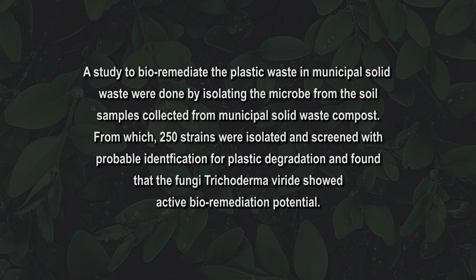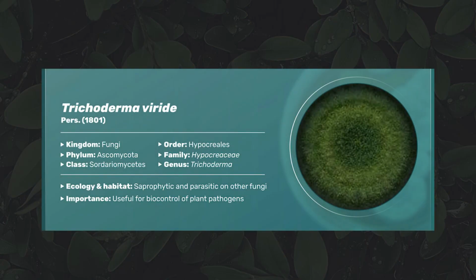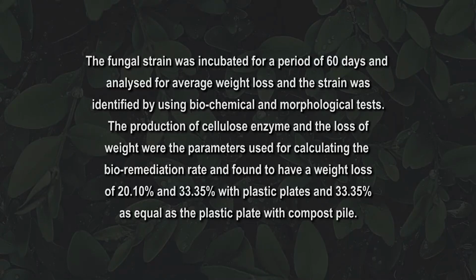Now, a study to bioremediate the plastic waste in municipal solid waste was done by isolating the microbe from the soil samples collected from municipal solid waste compost, from which 250 strains were isolated and screened with probable identification for plastic degradation, and found that the fungi Trichoderma viride showed active bioremediation potential. The fungal strain was incubated for a period of 60 days and analyzed for average weight loss, and the strain was identified by using biochemical and morphological tests.